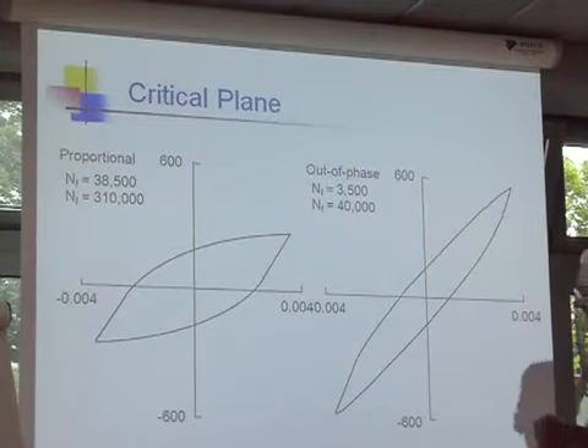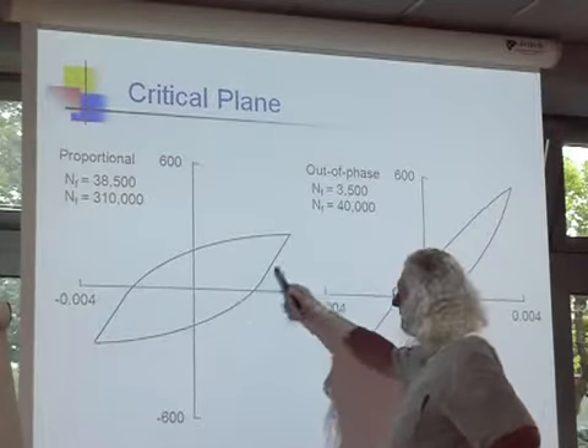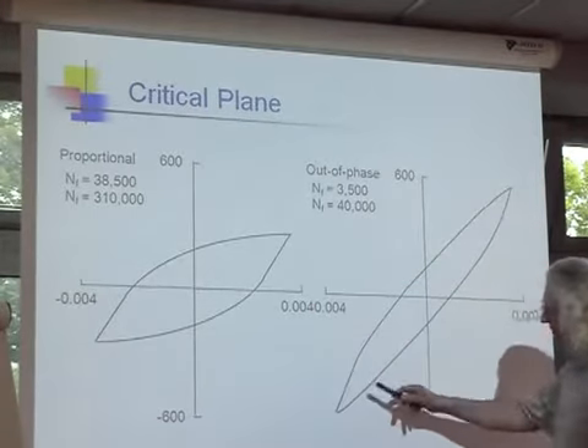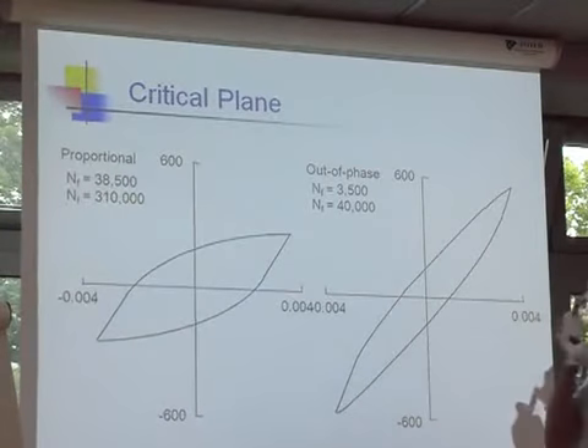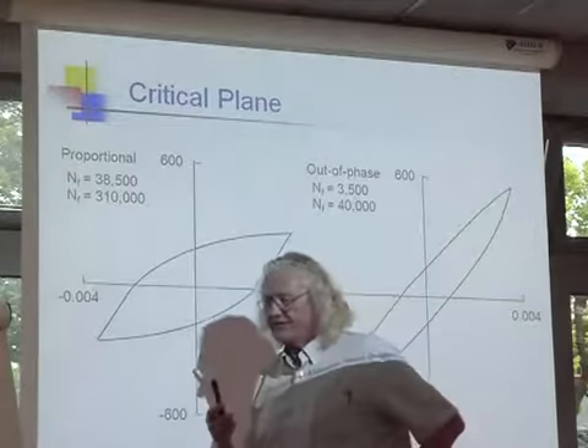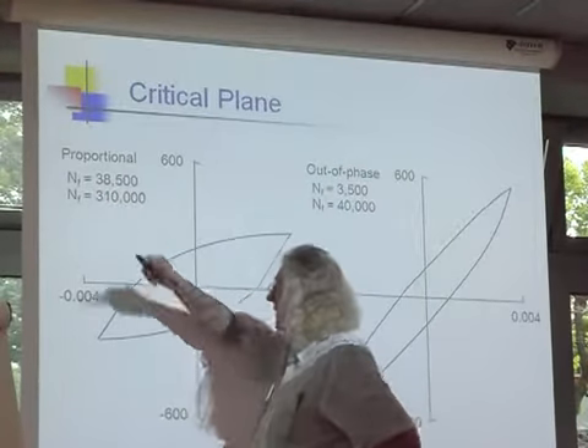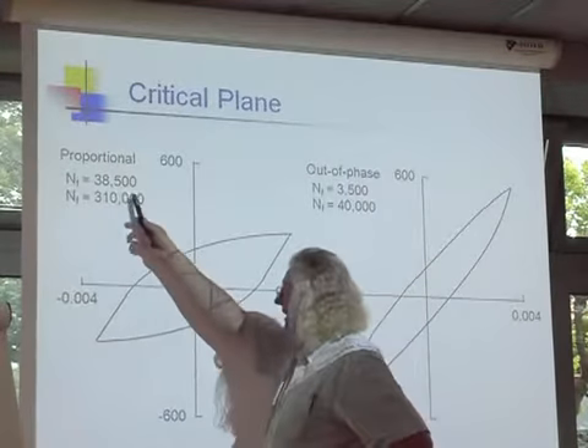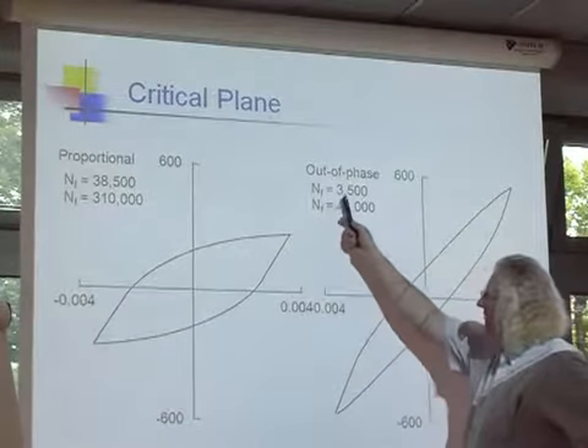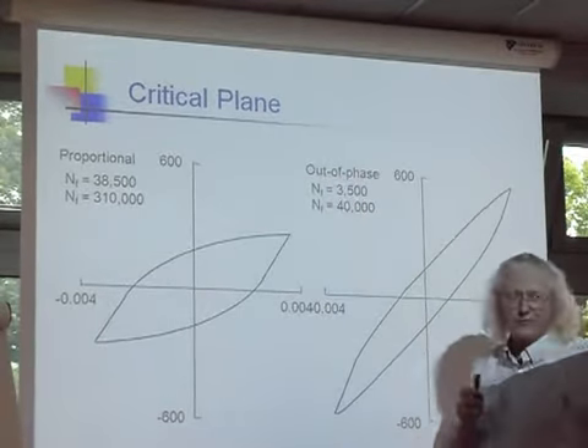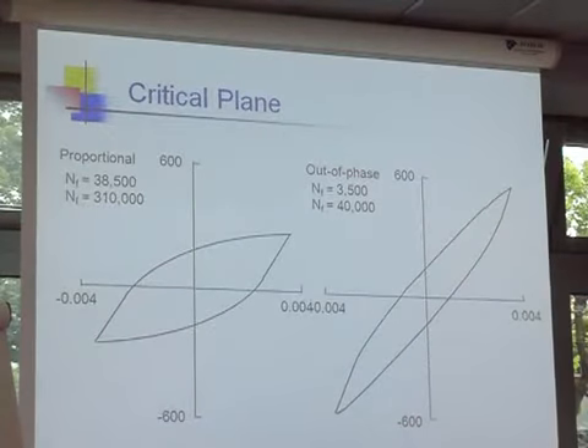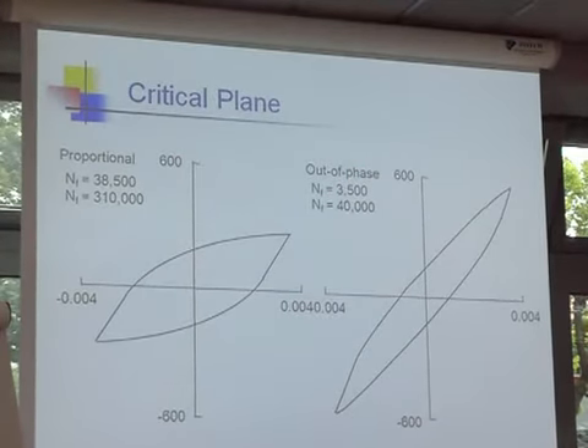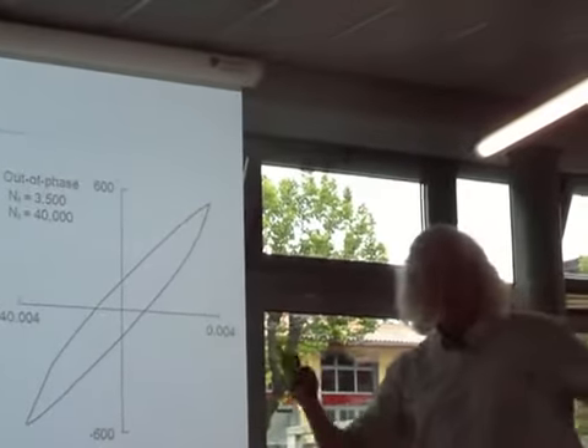There's the behavior on the critical plane for the in-phase loading. There's the behavior on the critical plane for the out-of-phase loading, same strain range. And we can see that we run a series of tests at a high stress, and so the lifetime here is about 38,000 cycles. And if we do this in the out-of-phase loading, the lifetime was reduced by a factor of 10. Not a bad prediction for our simple model, was it? Our simple model said maybe we would expect a factor of 30 difference, and we go in the lab and say, yes, it was a factor of 10. I think that's very good. Because I expect a big effect and I see it.